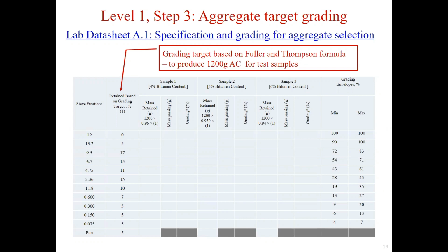You could use the Fuller and Thompson formula to calculate the target grading, and then work out the values for all three samples with bitumen content of 4% to 6%. We will practice one example by the end of this lecture.